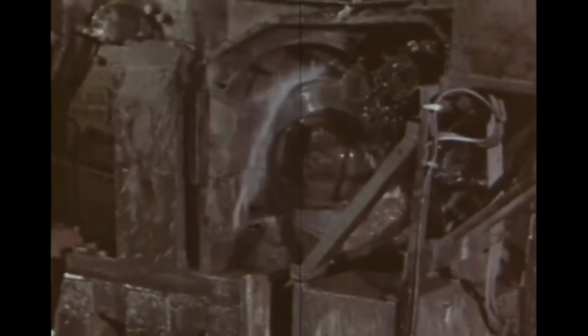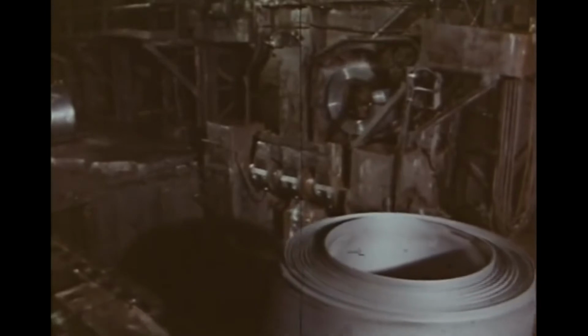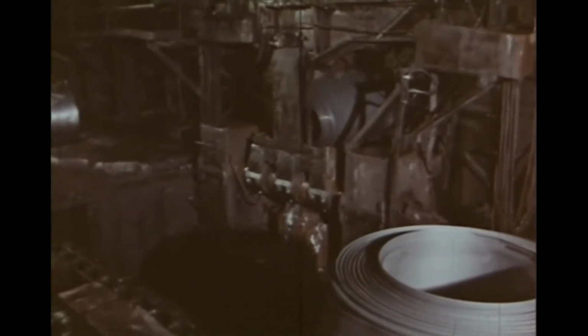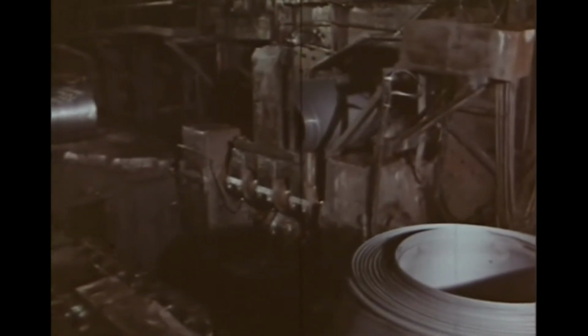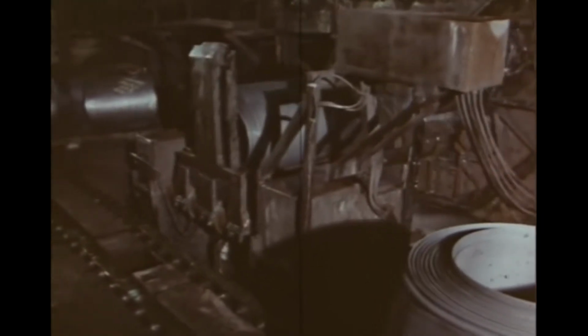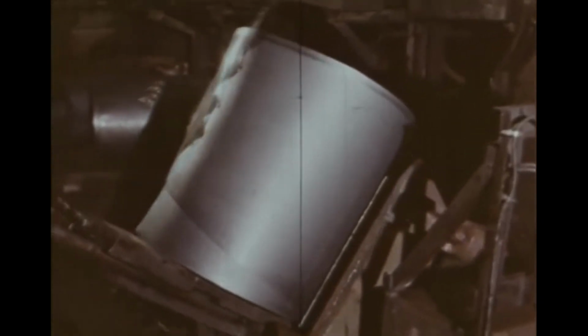Emerging at the end of the mill, the strip is cooled and then it is coiled. The result, something that finally begins to look like sheet steel. The original 16-foot slab is now over 600 feet long and about 1/10 of an inch thick. The whole process, from slab to coil, took less than 2 minutes.